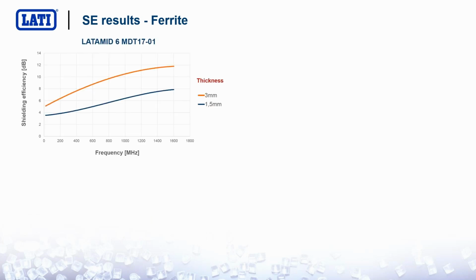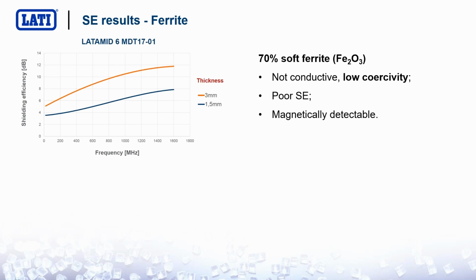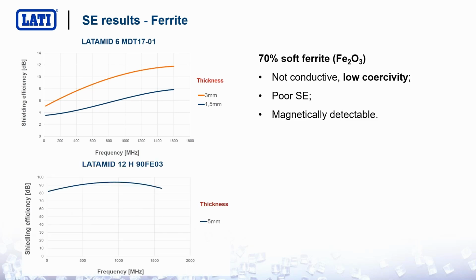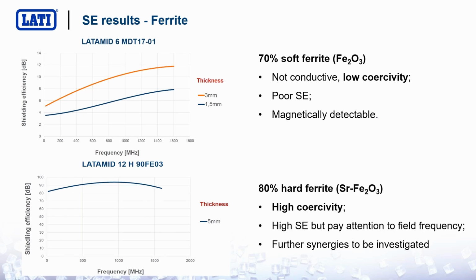The last results were developed on ferrite. We tested the so-called MDT17, which are magnetically detectable ferrites, and in this case it didn't work. And also hard ferrite, which is the strontium ferrite, which actually provided acceptable results. But we think there is a lot of improvement to be done with ferrites, especially when it comes to magnetic field absorbing shielding applications. And we also want to test what happens by mixing ferrites with steel fibers in order to have a compound which is providing very good magnetic and electric field shielding performance.